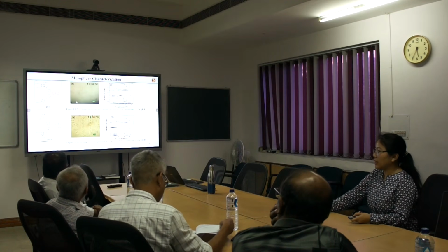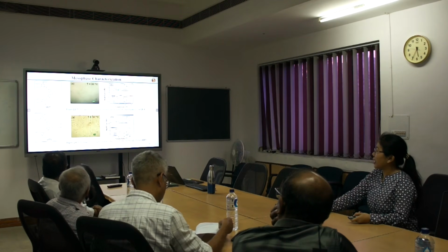Coming to the mesophase characterization, in the case of the QE series, where we have unsubstituted, cyano-substituted, and fluorine-substituted, we did not observe any birefringence texture, signifying that it does not show liquid crystalline behavior. And for QER2, the 6 and 7 positions have alkoxy, and the two alkoxy at this position did not show any characteristic feature of mesophase.